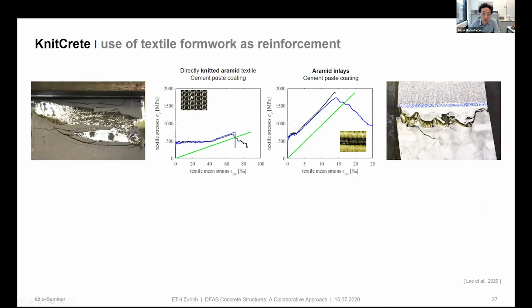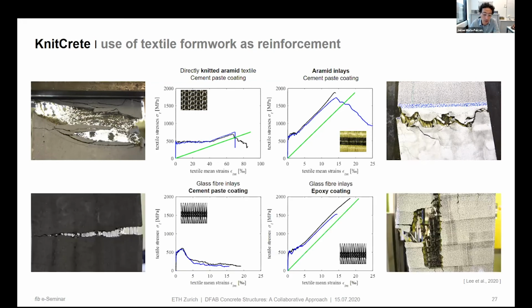So when we have just the aramid knitted textile, we have some hardening, but the behavior is not good. But we can also add in this knitted textile some straight inlays that give behavior similar to traditional textile reinforced concrete. And also we are checking what happens if we do a coating with cement paste or with more traditional epoxy. This seems to work better for glass fibers, with this traditional epoxy.